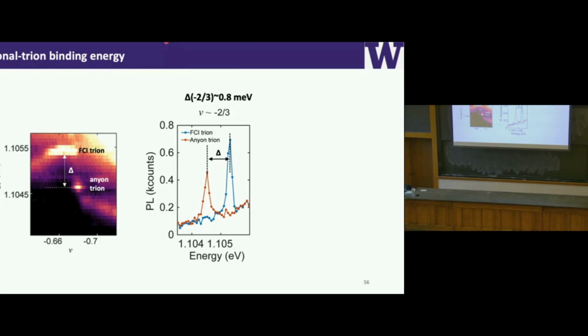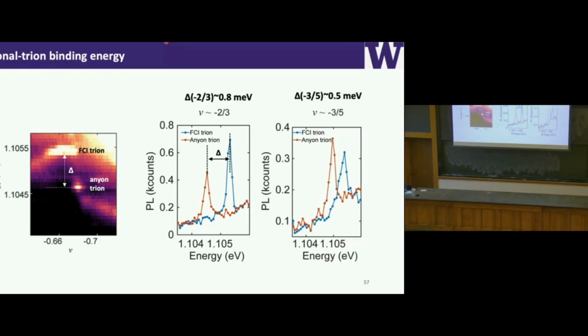Still, 800 microeV doesn't tell me the state is fractional charge. So what we can do is compare the other filling factor, which is 3/5. From there, we can also get the binding energy of the 3/5 state, about 500 microeV. Now these two numbers will be meaningful, right?